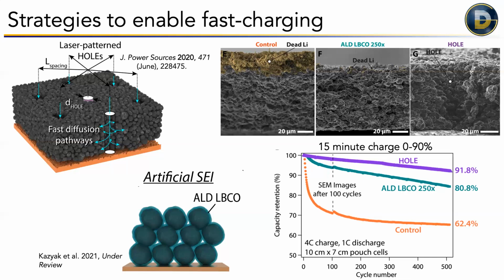Yeah, that's exactly right. And the reason why, it's not that your car battery couldn't be charged in 15 minutes once. It's that it would be this orange curve, right? If you did it 50 times, you'd only get 200 miles of range instead of 300 potentially, right? So that's the problem, you get this lithium plating. So Chevy has said, okay, we're just not going to let you charge it that fast, because we're not going to let this happen. It's also a safety risk because you have this metallic lithium around, but they don't want your battery to fade like that, because then they'll have to replace it on warranty or whatever. So they limit it. And that's why I think these types of technologies are really promising.